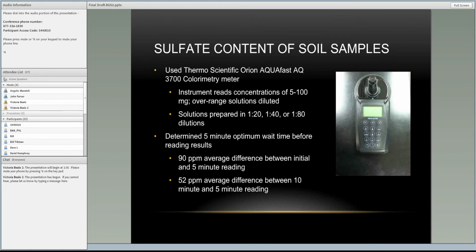And we ultimately determined that 5 minutes when using the barium chloride packet is the ultimate wait time. As you can see down here, the difference between the initial reading and the 5-minute reading results in a 90 parts per million difference, the average results. And the difference between waiting 5 minutes versus 10 minutes is a difference of 52 parts per million. So just due to time and everything, especially if you're testing a lot of samples and you want a good sulfate reading, 5 minutes is a good wait time, the optimum wait time to use.